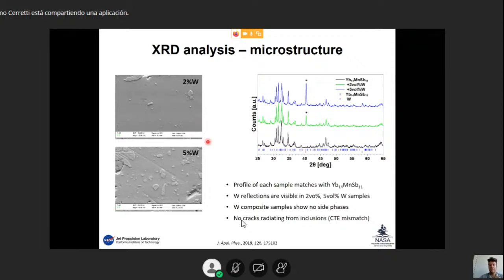When we have such a big CTE mismatch, already after synthesis you would be able to see cracks propagating from the inclusion throughout the matrix. What you see here is just scratching due to the polishing of the surfaces, the tungsten being much harder than the matrix material. When you polish it, sometimes you pull out some inclusions, and then basically they scratch the surface, which is softer, the surface of the matrix.